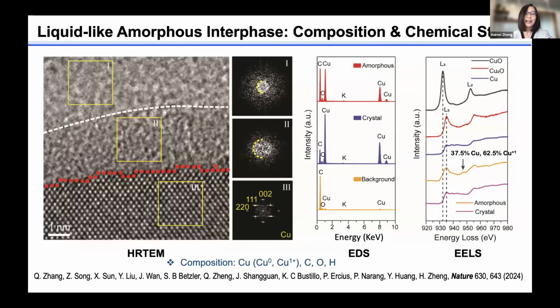As I mentioned, because we can do cryo-EM and fast freeze this reaction state, we can look at this amorphous state very carefully. This shows high resolution imaging of the copper state with an amorphous background, and we can do EDS and look at copper with Cu 1+ and Cu 0, and resolve this very challenging puzzle in the field, resolving the different compositions and ratios. We did many different control experiments to resolve the composition. I won't go through the detail. It includes copper and also carbon, oxygen, hydrogen. It suggests this amorphous state is a copper complex.